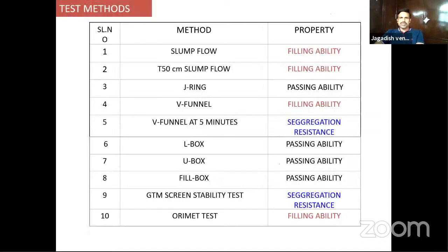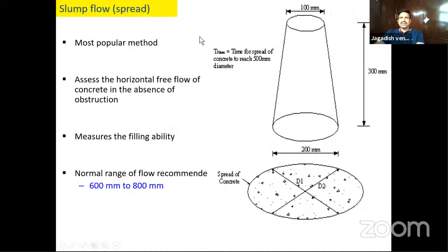Some of the test methods we use are slump flow and T50 centimeter slump flow, which measures filling ability. Similarly, there is the V-funnel, where you do two tests: V-funnel at 0 minutes and V-funnel at 5 minutes. And we do the L-box test, U-box test, and fill box test. These are all passing ability tests. And you have a GTM screen stability test and Orimet test. Okay, some of the tests I'll show you now. You know the slump cone, this is a slump test I'm going to explain.